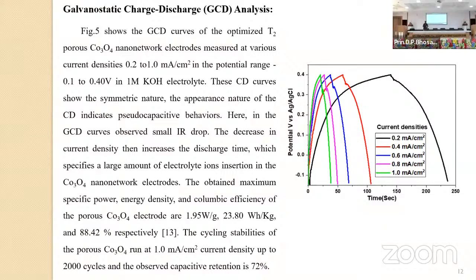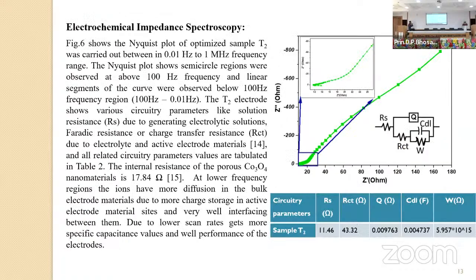Okay, then another characterization of the supercapacitor is galvanostatic charge discharge analysis. This is very important because, you know, cobalt oxide material can be a battery material or a supercapacitor material. Using this characterization we can tell whether the material is a pseudocapacitor or battery-like material. This shows the material is symmetric, and it shows the pseudocapacitor nature at various current densities, that is 0.2, 0.4, 0.6, 0.8 milliampere per centimeter.